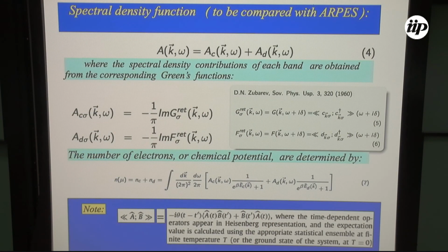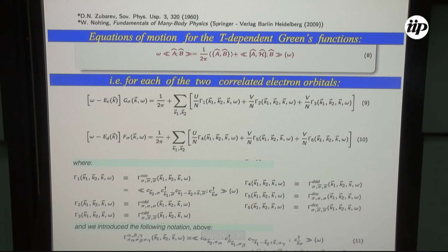And how do we get the Green functions? Well, we use the Zubarev approach of equations of motion, with Green functions which are defined as a function of temperature. So they depend on mean values at finite temperature. And we used the equations of motion for those. In principle, we have one for the C band of electrons, another for the D band of electrons. And the other terms in the equation of motion are coupled to higher order Green functions. And there you can decide where you would like to decouple the equations and finish. And there you get different approximations for the results.